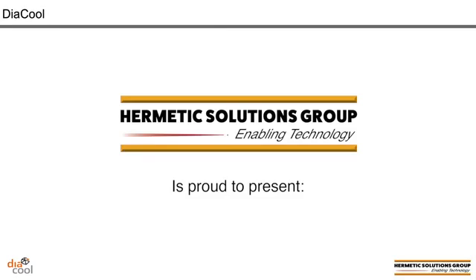So this nearly concludes today's presentation on Diacool. However, I wanted to show you this video that gives you a little different viewpoint of how well Diacool acts as a passive thermal spreader. In the case of this video, I'm going to show you two samples of material, one being a pure copper sample and one being a copper diamond Diacool sample. In this case, I've got a resistor mounted to the backside of two identically sized substrates, and I'm going to fire up that resistor. And the idea here is to see how long it takes this product to thermally dissipate up to 80 degrees C and then cool down to around 50 degrees C.